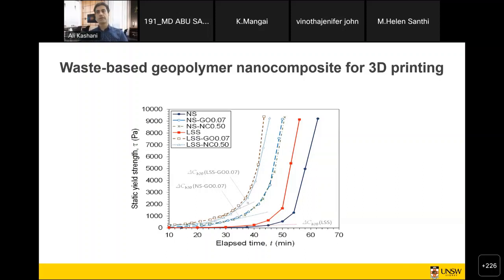The property that we really want in terms of the rheological requirement of 3D printing, if you're not familiar with this rheology term, is the structural buildup and the yield stress buildup of the material, especially at early ages. It is not high. And we need that in a free form condition of 3D printing because we're putting loads of self-weight of those 3D printed layers on the bottom layers. So as time passes, they need to get some early strengths in order to build up on that and support the successive layers.